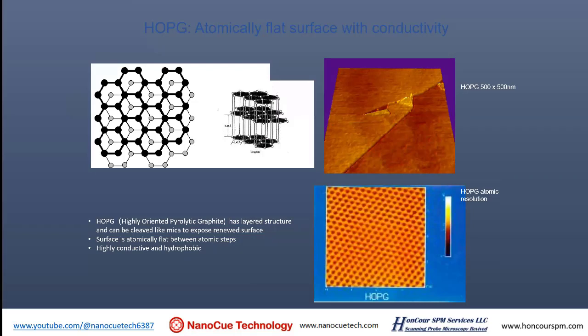Here's another very good substrate I suggest you use, and that's HOPG, graphite. One of the characteristics of graphite is that it is a very easy to clean substrate. That's because graphite is also made of sheets of graphene, right? Sheets of carbon honeycomb structure. And between the sheets, the bond is very loose. So if you use a tape to remove the top layer of the graphite, the surface is clean.